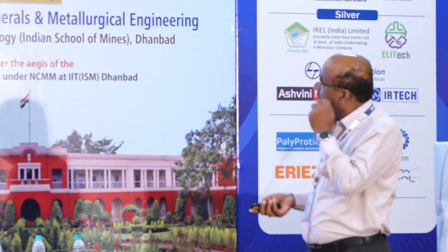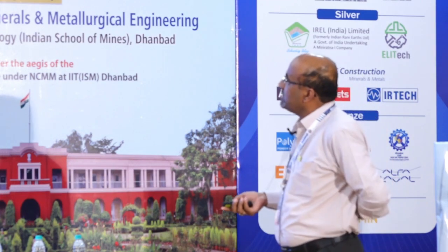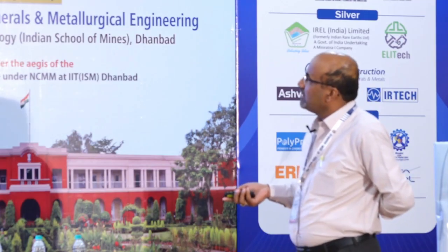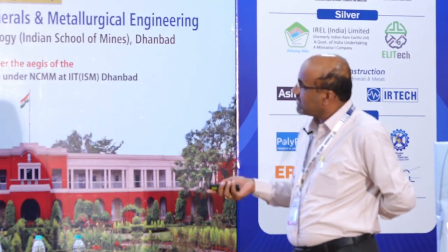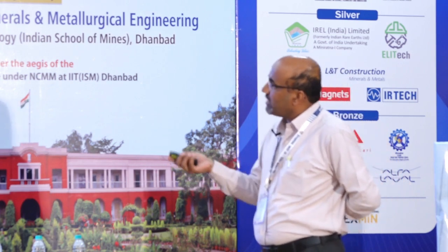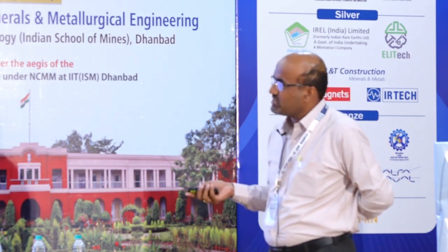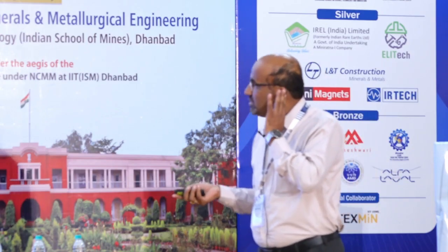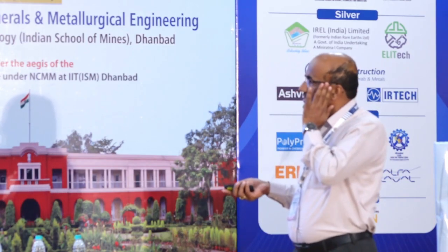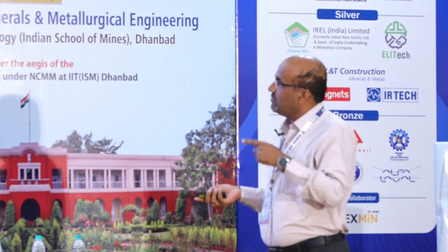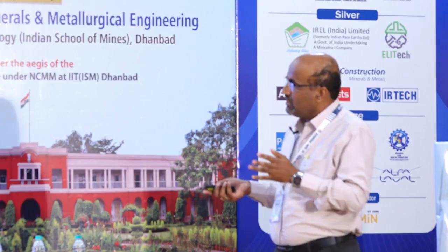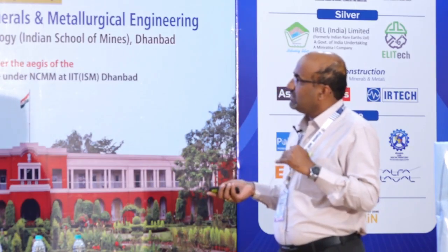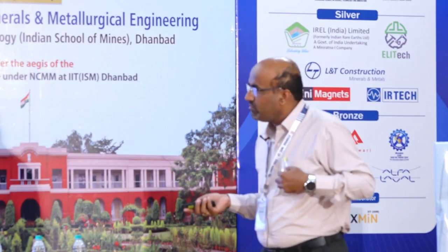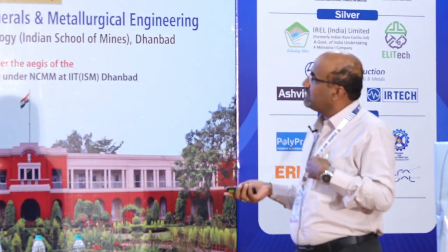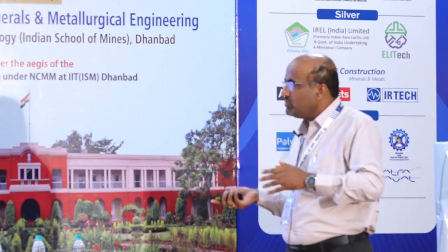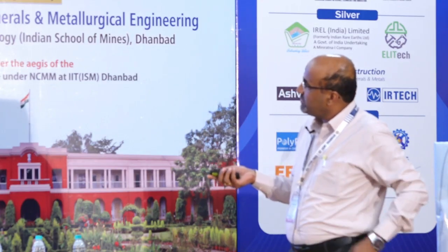This is a typical problem coming from IREL. They want to separate yttrium from HREs in one of their streams. The current state is like this: earlier a thiocyanate based SX process was given, and it has provided quite good separation factors for HRE over yttrium. The problem is that we are adding thiocyanate to give selective recovery, but the management of hazardous thiocyanate is a big problem. Getting a license for that is a little tricky, and because you have to manage thiocyanates, it becomes a costly process.